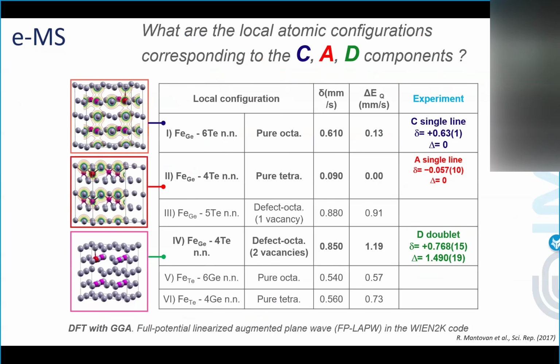And then we need to understand where it comes from. DFT was absolutely necessary in this case. And at the end, we identified the single line of the amorphous state as being the iron substituting germanium, and looking at what happens around it, at the tetrahedral site.